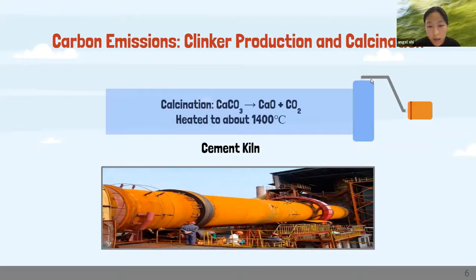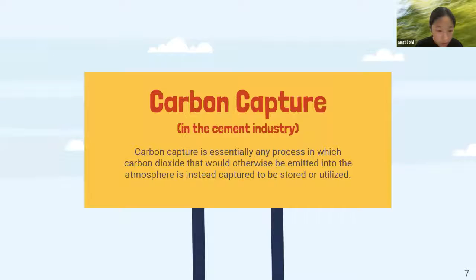of carbon dioxide. The clinker is ground with additives such as gypsum, which decreases the amount of clinker, and those additives also control setting time and give strength to cement. And the calcination process thermally decomposes calcium carbonate, which is found in limestone, to calcium oxide and carbon dioxide, which is released as a byproduct. Next, Max will talk about the carbon capture process.